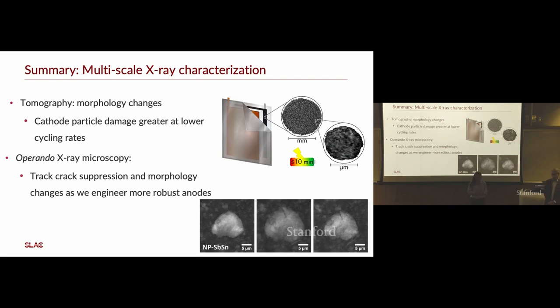What about the dead lithium? So people always say the dead lithium layer. Lithium is also difficult. The higher up you go in the periodic table, the harder it is to see with an X-ray. So lithium is very difficult to see. And that's why we used the lithium mapping that I showed you at the very beginning, using X-ray diffraction to study the dead lithium. Lithium is crystalline, so you can see with diffraction where lithium is and map it out in real space by moving your sample through the beam.